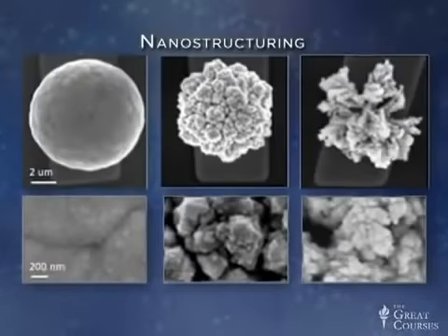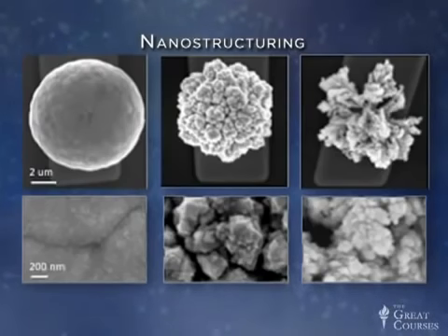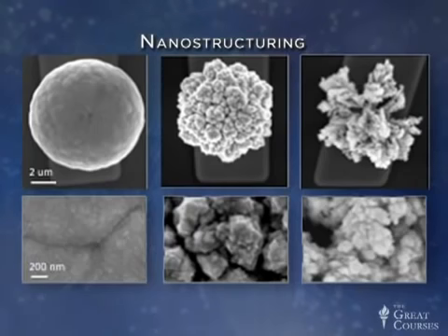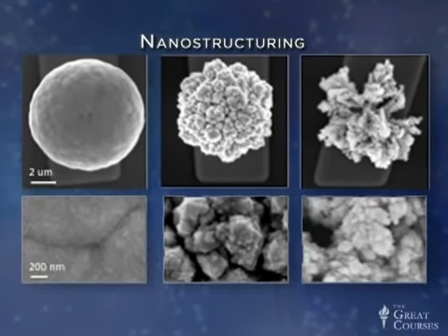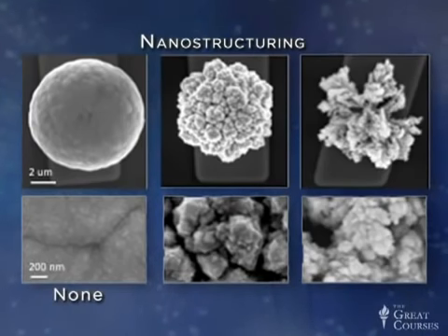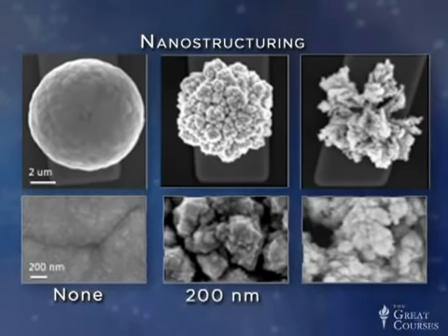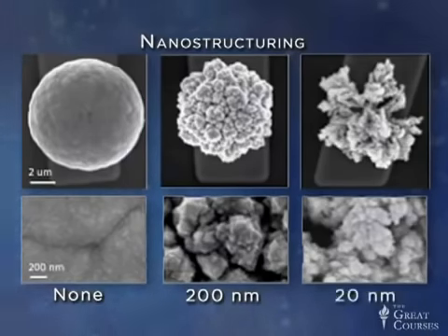So you're looking at images that are collected using scanning electron microscopy, and these are 3 different sensors that we made, and they were all made side by side on our chip. The one that is on the left has no nanostructuring. It's basically smooth. While the one in the middle has pretty large nanostructures that are about 200 nanometers. Now, the sensor on the right has very fine nanostructures that are about 20 nanometers.